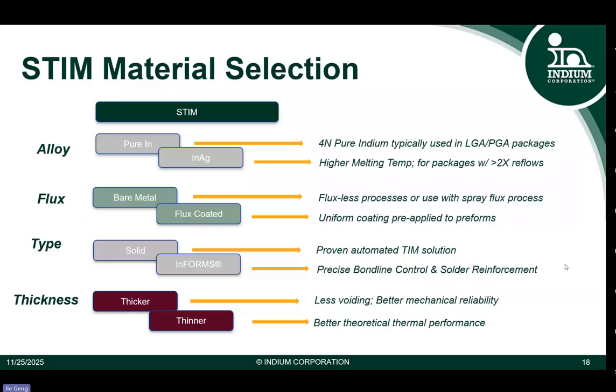And here I showed the factors you have to consider when selecting the preforms. So first is the alloy, so indium or indium silver. That depends on the specific applications. And the next is the flux, either bare metal or flux coated preform. Then the type is solid or InFORMS. So the frame can help the bond line thickness to be uniform. And then the last variable is the thickness. How thick is good for your applications. So those are the things you have to consider.